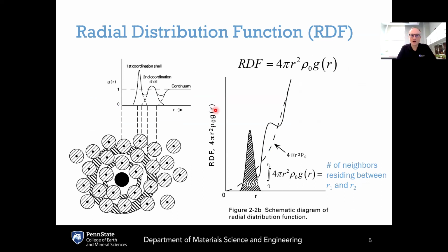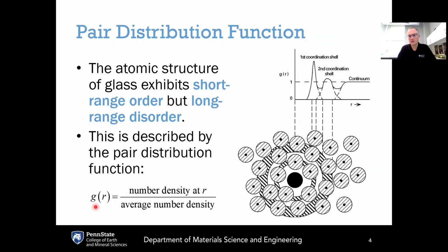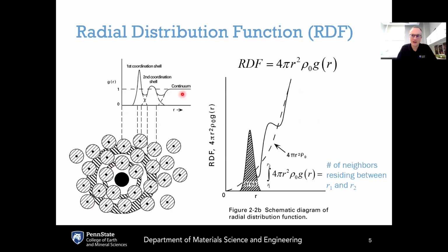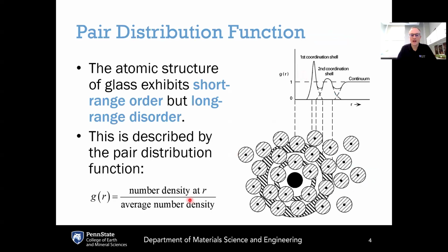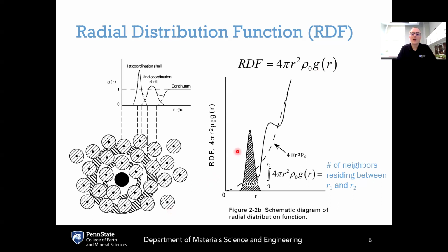Now, what I just described was g(r), which is the pair distribution function. You will often see in the literature another function called the radial distribution function, or the RDF. Some people will use these terms interchangeably, using the term radial distribution function to mean the same thing as the pair distribution function g(r), and in that case it would be plotted exactly as shown here. Strictly speaking, though, the radial distribution function is the pair distribution function g(r) multiplied by 4 pi r squared times rho 0, which is the average number density. This 4 pi r squared is the surface area of this shell that is expanding out.